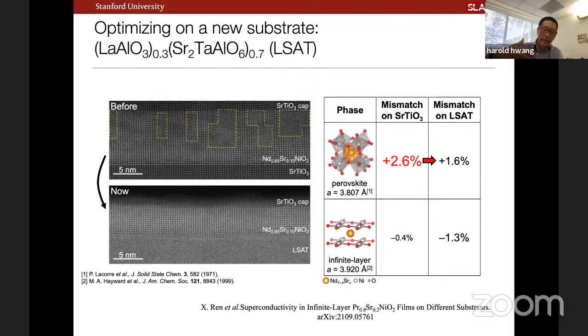And so the growth is kind of a compromise. Do you want to make the perovskite very happy or the infinite layer phase very happy? If we go very far off of this window, to the levels that would be relevant for inducing a spin state transition, it's not completely clear to me whether we can maintain stability. So that would be, sorry to say, a mundane but very real experimental constraint. I certainly think this is an exciting idea. I should say that there was also a pressure paper on the archive. It's a thin film sample, but under hydrostatic pressure, where the main discussion was that the scale of Tc apparently goes up quite a bit. One could imagine that gives you a c-axis degree of tuning that could be used. Right now we can't address that experimentally, but the experimental constraint is really this issue of moving too far away that we can't stabilize.